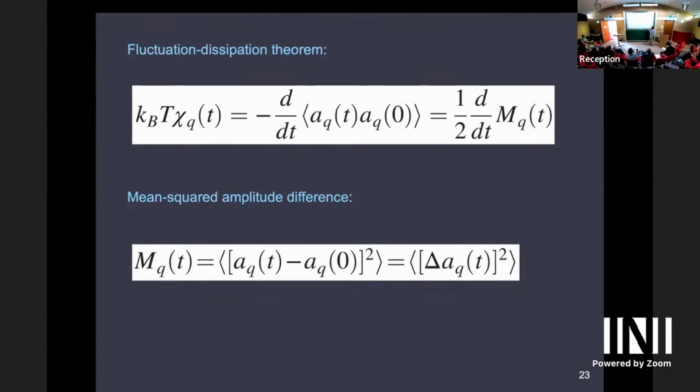So what's easier or better experimentally is to use the time-dependent mean square displacement for the amplitudes, and then you have to take a derivative of that. So that makes it a bit tricky numerically. You have to be careful about how you do the derivative. But when you do that, you get more symmetric results. But in the end, that's the way we evaluate the data.